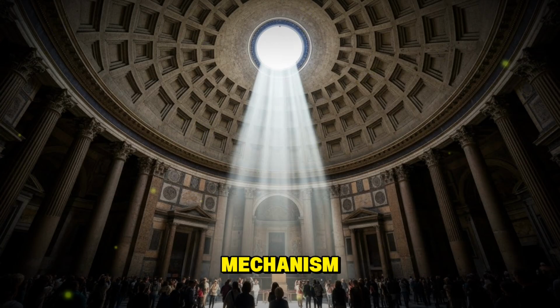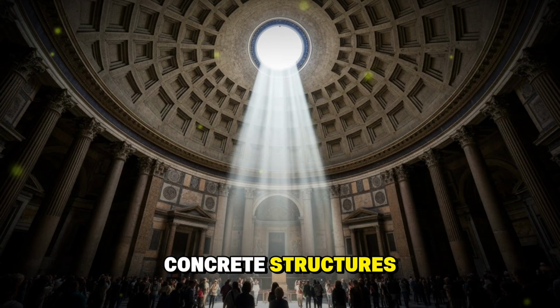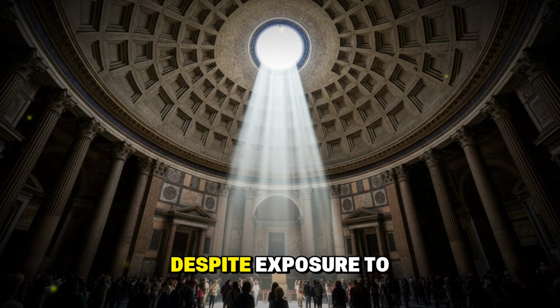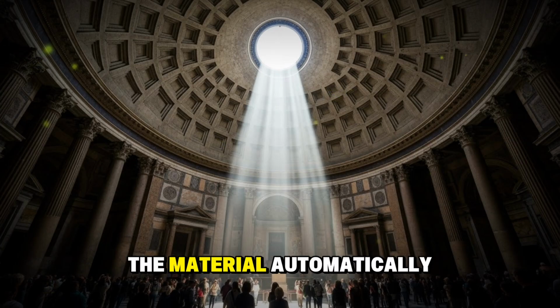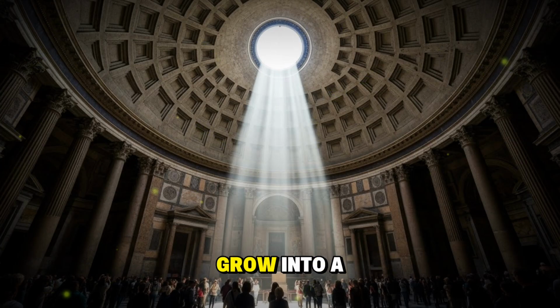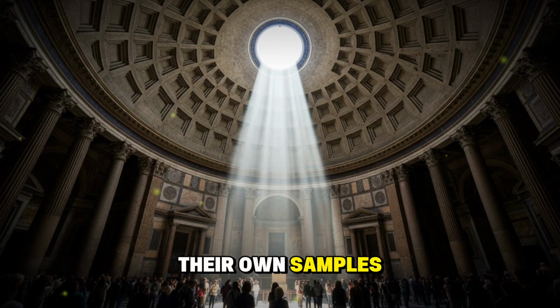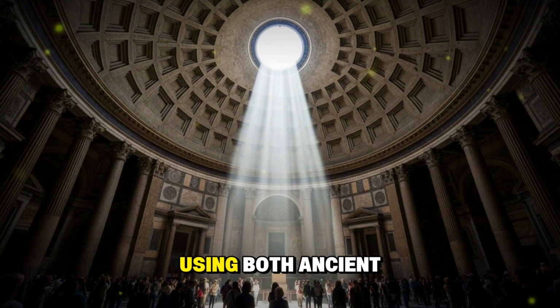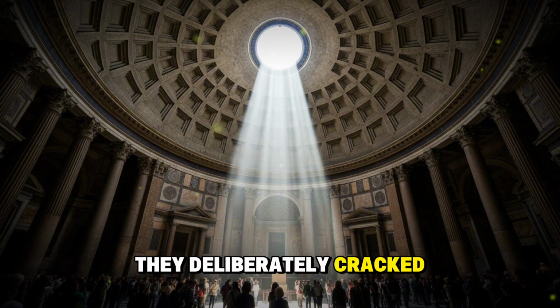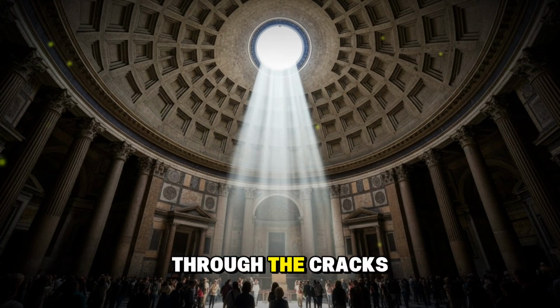This self-healing mechanism explains why Roman concrete structures have survived so long despite exposure to harsh conditions. Every time a small crack formed, the material automatically sealed it before it could grow into a major structural problem. The concrete responded to damage by fixing itself over and over for centuries. To prove this mechanism, Masic's team created their own samples of hot mixed concrete using both ancient style and modern formulations. They deliberately cracked these samples, then ran water through the cracks.